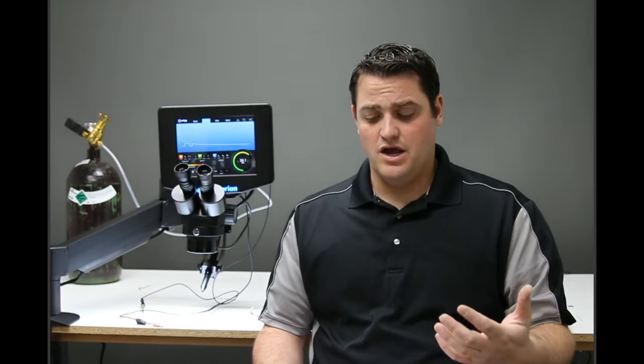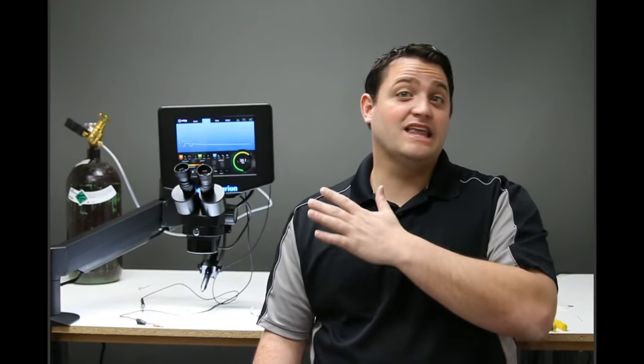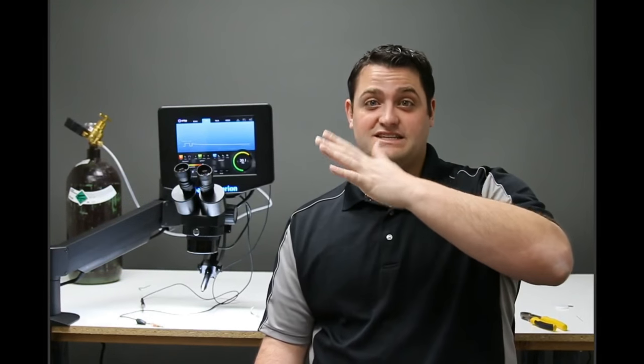Another thing to keep in mind when welding silver is that it's very mobile. So when we heat it up and it's at that molten state, it likes to move around really, really easily. Even the argon gas flow, if we have it too high, is enough that the flow of argon gas pressing against the surface will cause it to deform a little bit and won't give us that perfect weld.